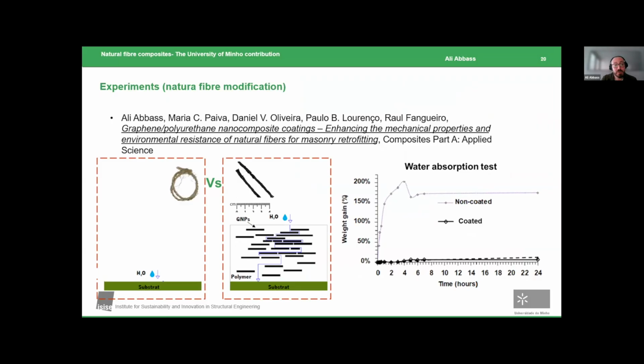So we'll start with the water absorption test. You could see the non-coated fibers reached saturation after 6 hours at almost 150% weight gain due to water absorption. While for the coated fibers, we reached saturation at 6 hours at 10%, and that was maintained up to 24 hours. So this is quite water resistant.